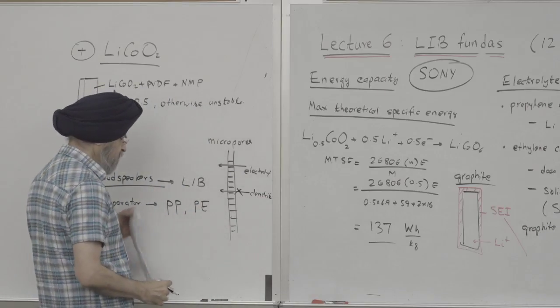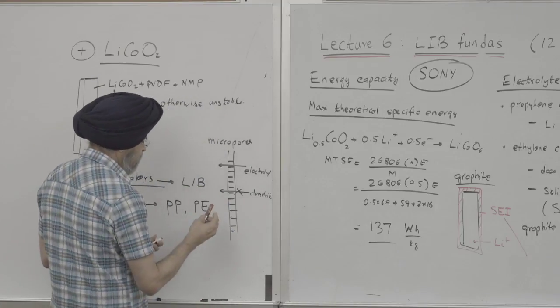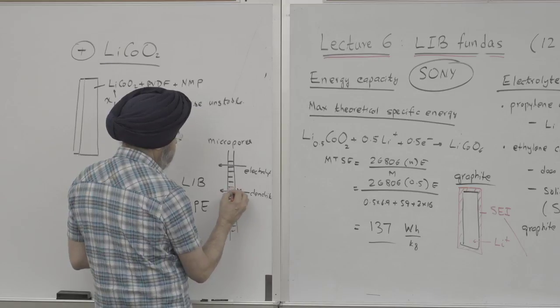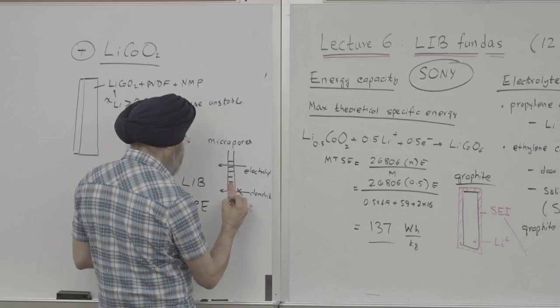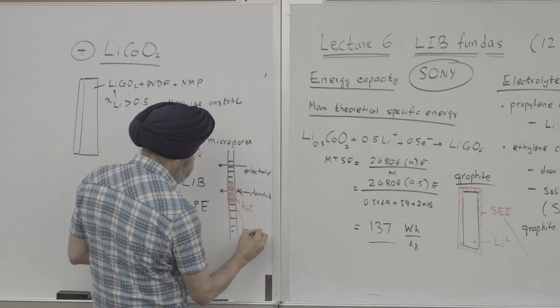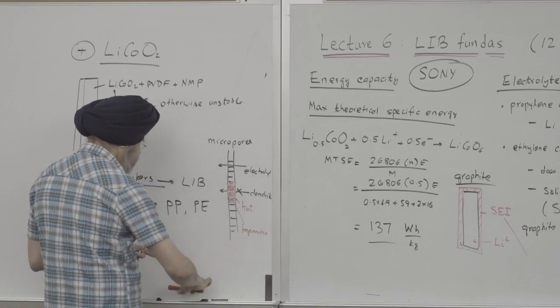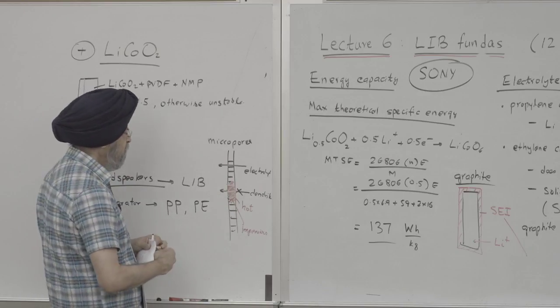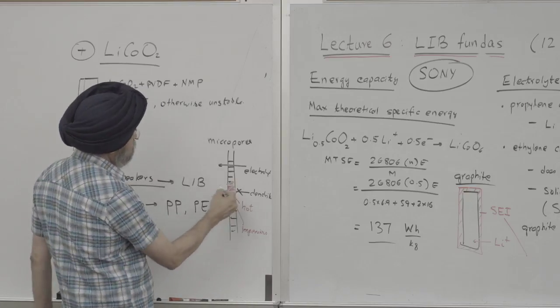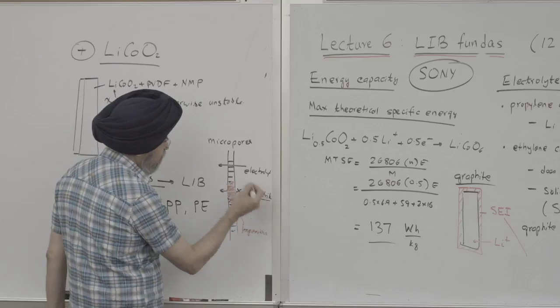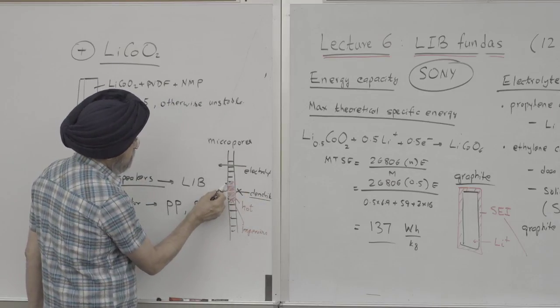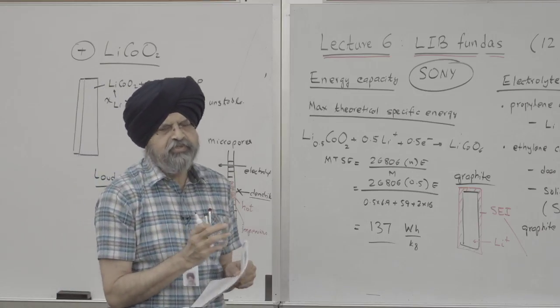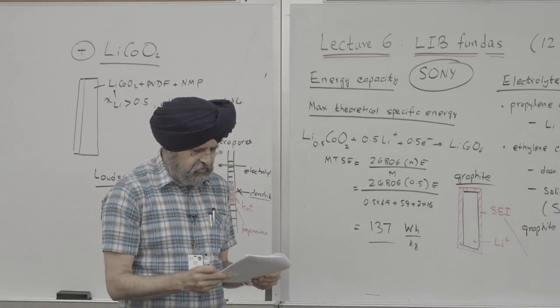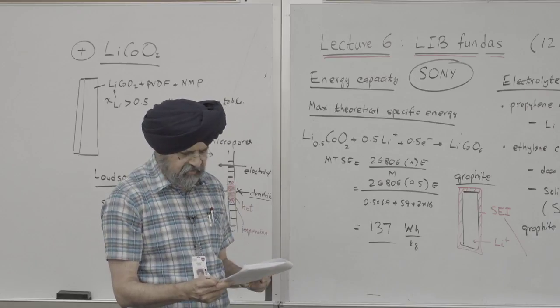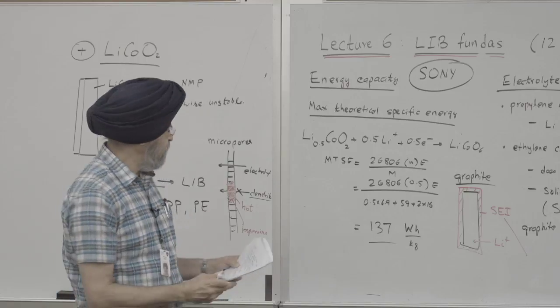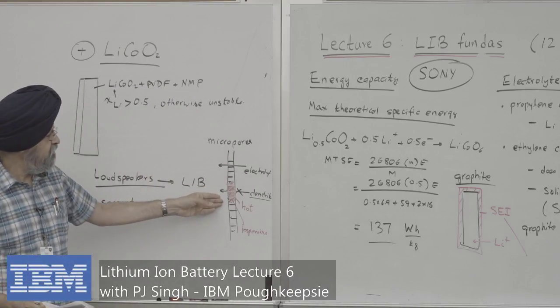Another big deal was, in case a dendrite went through, and let's say there was current crowding and this region became hot, then this would melt and form an impervious membrane. So if there was short circuiting between the two electrodes, for whatever reason, because of dendritic growth or something else, the separator would get hot and the micropores would collapse and it would become an impervious membrane. I think there's a term they use for that. I can't find it right now. Oh, yeah, thermal shutdown. So they call this thermal shutdown. That was another discovery made by Sony.